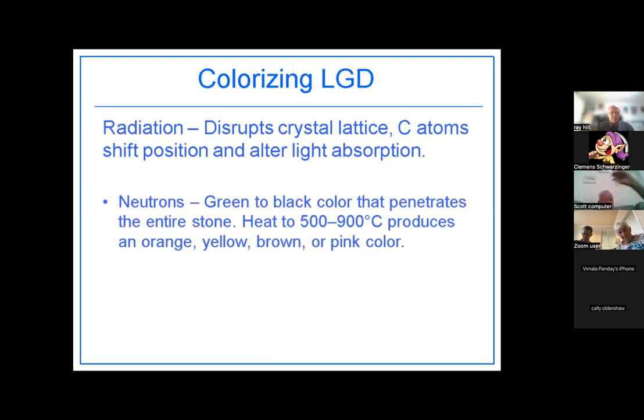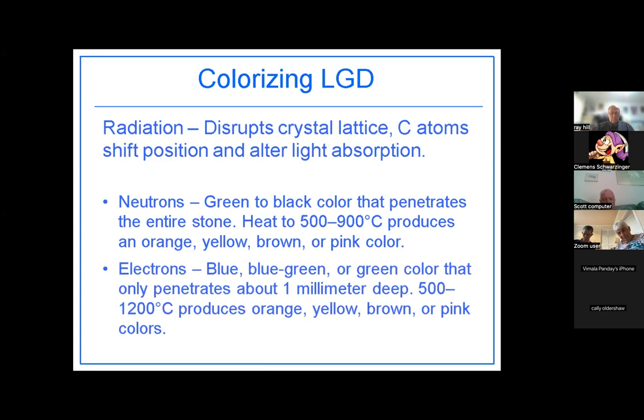When you're talking lab-grown diamond, they use neutrons. And you can see here it penetrates through the entire stone, making your colors anywhere from green to black. And then you can throw in an additional heat treatment up to about 900 degrees centigrade to produce some different colors. This is still a little bit in its infancy as far as colorizing lab-grown diamonds. I'll talk about that a little bit more.